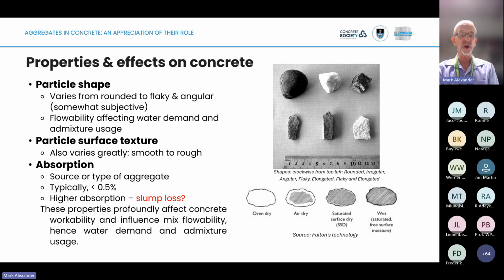Okay, this is the definition of water requirement. It really is the amount of water required in 1 cubic meter of concrete to give the required workability. That used to be a 75 slump, but these days admixtures have hugely influenced this whole issue. So this question of water requirement has become a little bit moot because we can do marvelous things now with admixtures that we couldn't do when water requirement was first defined. And so they are really our process control parameter in many cases, although we always want a low water content, as we'll see. The fine aggregate always has a larger influence on this water requirement because of its larger particle surface area.